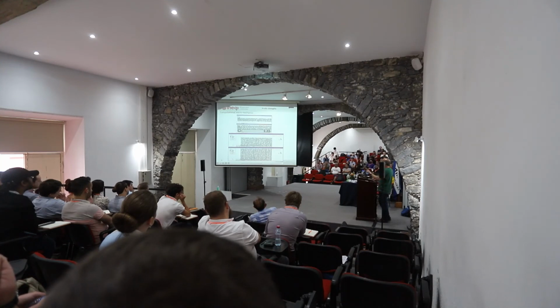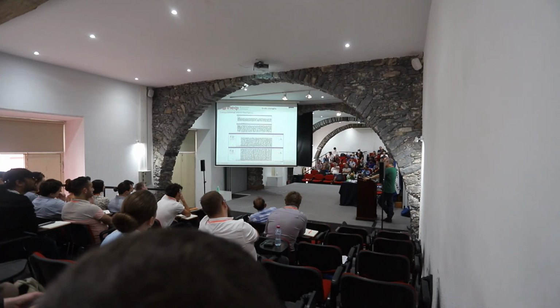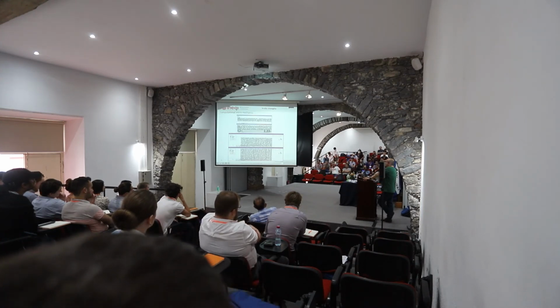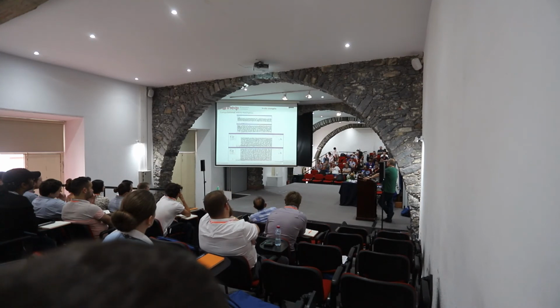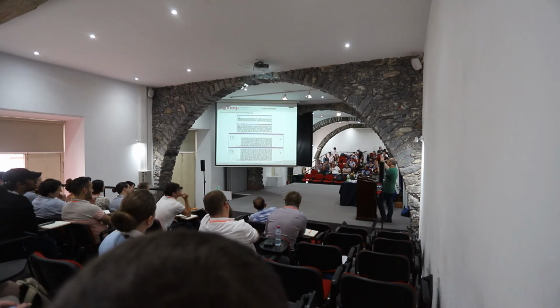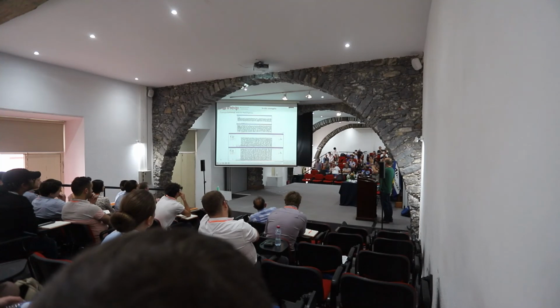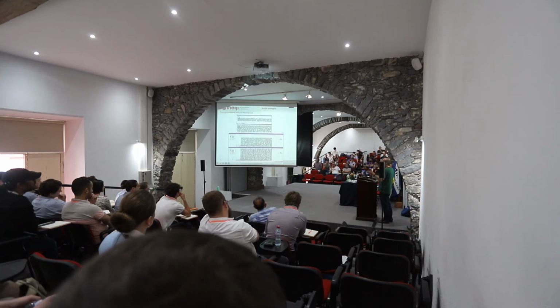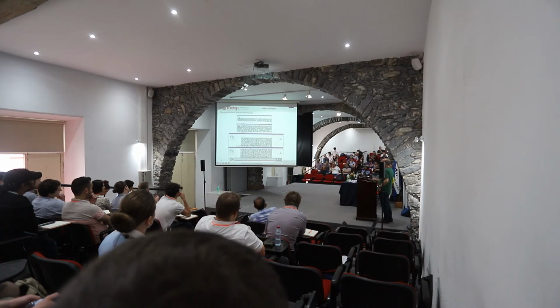One interesting thing here, further validated with tests we performed at the synchrotron in Grenoble, is that if you have very thin laminates, like 20 microns or so, you don't get cracks through the thickness. You get a network of fiber matrix debonds. As you decrease the thickness, the crack density is higher, and you probably understand this from simple fracture mechanics. Why? Because imagine that you have this large crack, and you have this triangular region there and there.